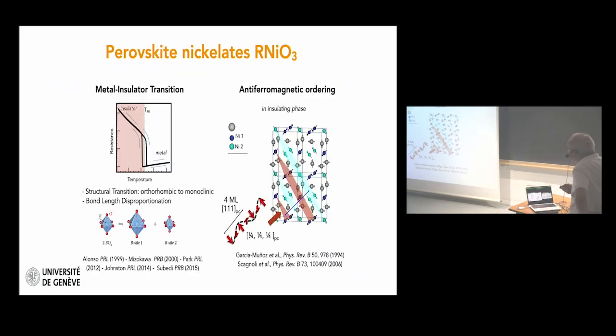So as I said, they are well known for their metal to insulator transition, and this transition is accompanied by a structural transition, a breathing mode. So every other octahedron expands and the other contracts. At low temperature, and this was described by Andrea yesterday, they develop a quite complex antiferromagnetic state, which has the peculiarity to develop along the 1-1-1 direction with a 4-unit cell periodicity. And this will be important in a minute.